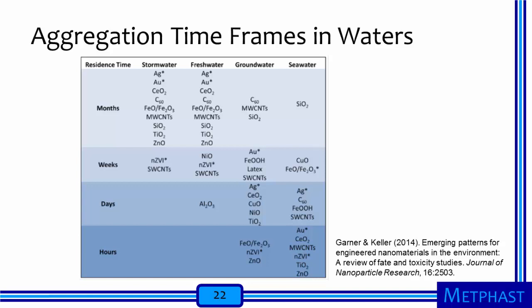Garner and Keller reviewed the existing literature and classified the time frames required for aggregation of engineered nanomaterials in aquatic systems as a function of material composition and type of water. In stormwater and freshwater, engineered nanomaterials aggregate slowly because of a relative lack of ionic strength and organic matter in the water. Thus, the residence time required for aggregation is long, requiring weeks or months. For groundwater and seawater, which have higher ionic strength and more organic matter, aggregation time is much shorter, requiring only hours or days for many nanomaterials.